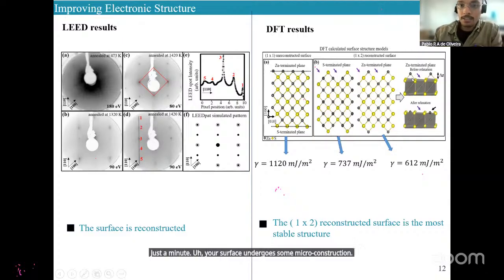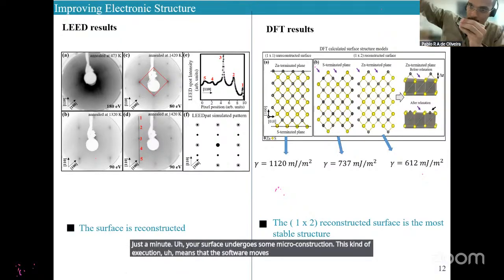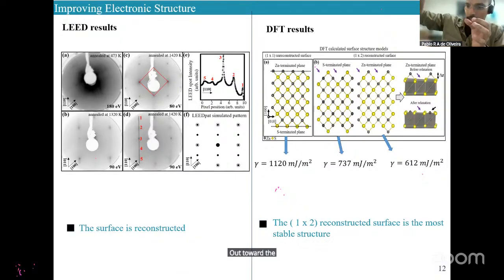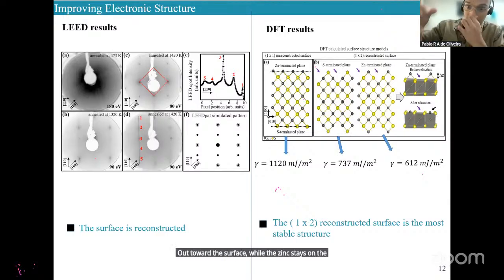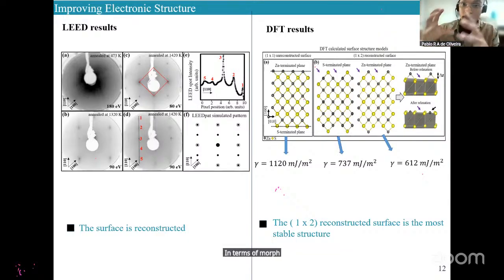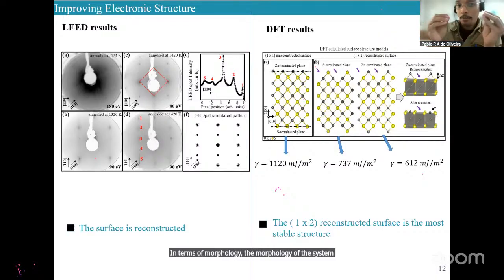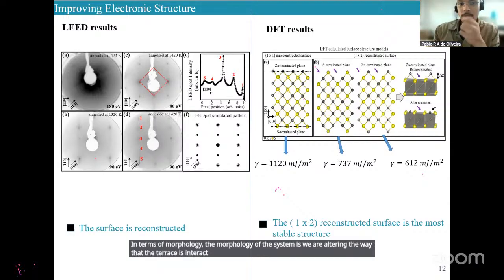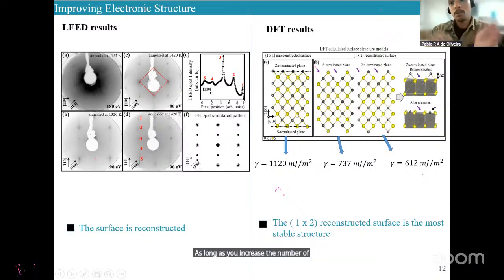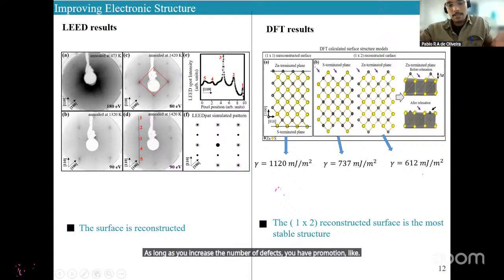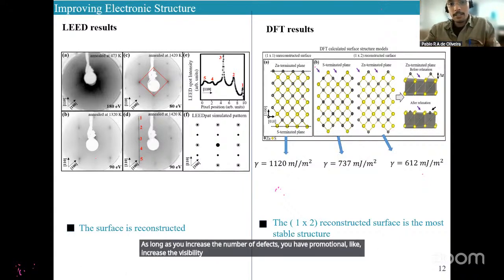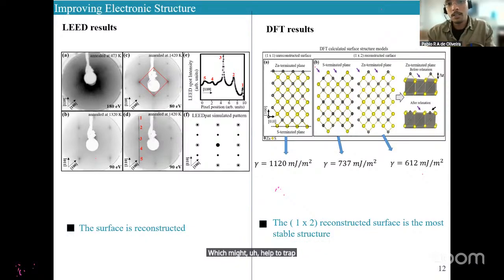This kind of reconstruction means that the sulfur moves outward to the surface while the zinc moves inward. In terms of morphology, we are altering the way that the terraces interact with each other. As you increase the number of defects, we are promoting more terraces in the system, increasing the vicinity of the ZnS surface, which might help to trap other molecules like oxygen, CO2 and CO. That's why we have this high affinity.